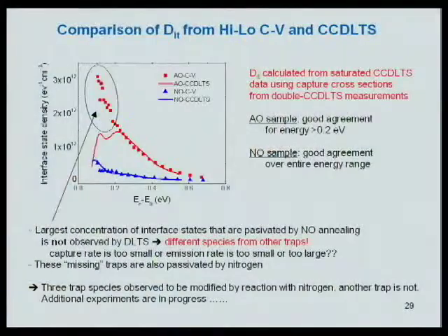Okay, what we did was calculate then the interface state density from our DLTS data. And what we find for the oxidized sample, we get this curve. And here I'm comparing it to the standard curve that I showed you before. This is a linear plot now. And what we find is we get very good agreement for energies greater than 0.2 electron volts. But for some reason, we're not detecting the large number of traps at lower energies.